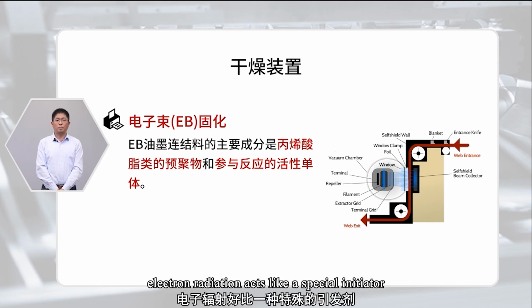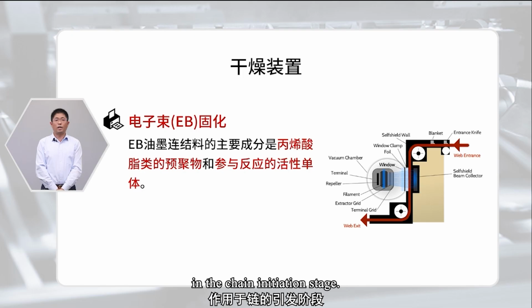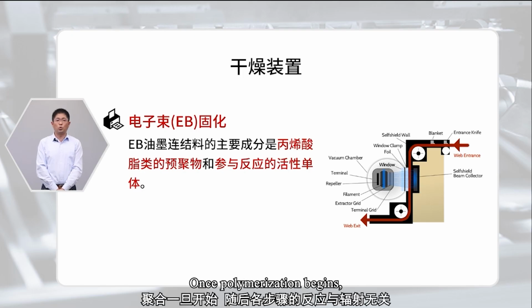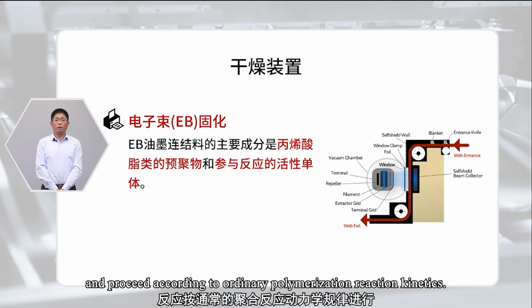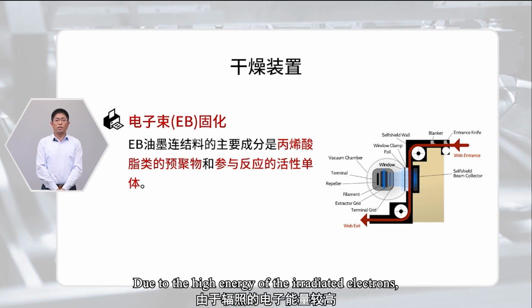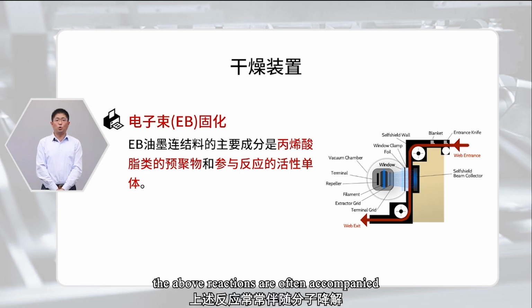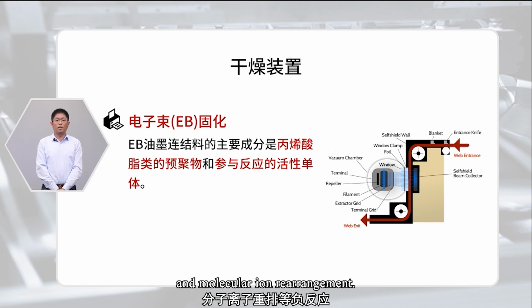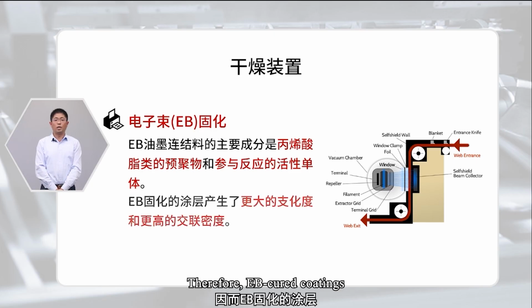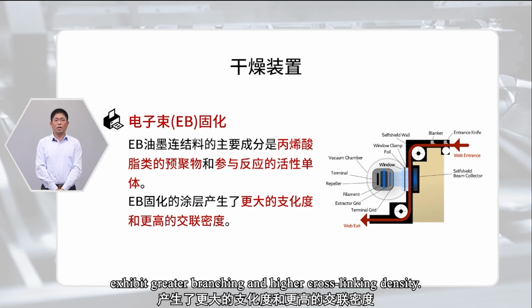In the entire process, electron radiation acts like a special initiator in the chain initiation stage. Once polymerization begins, subsequent reaction steps are independent of radiation and proceed according to ordinary polymerization reaction kinetics. Due to the high energy of the irradiated electrons, the above reactions are often accompanied by side reactions such as molecular degradation and molecular ion rearrangement. Therefore, EB-cured coatings exhibit greater branching and higher cross-linking density.